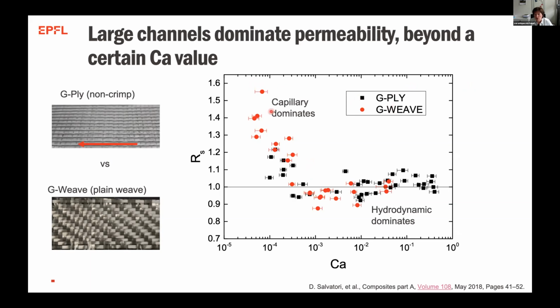And in particular, also for the G ply and the G weave, which is easier because it's a more narrow fabric. And then if we go above a certain value, we tried everything and we wanted it to go down. But in fact, what we see, because the hydrodynamic effect dominates, and in particular for the G ply, is that these big channels are really dominating the flow. Whatever we do, if we go super fast, we measure the same permeability because it's the permeability of the big spaces that is giving the value.